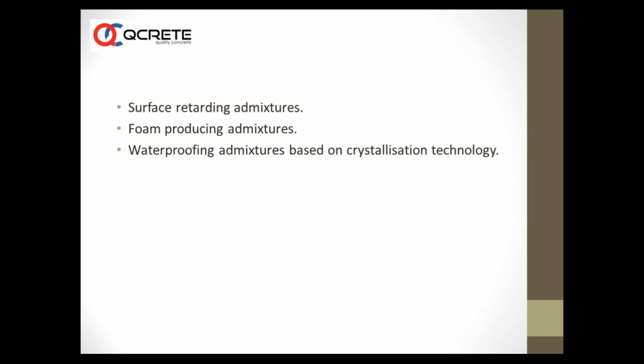Then you have surface retarding admixtures, used when you need architecturally or aesthetically pleasing concrete. You coat this set retarding admixture on the form liner or formwork. Concrete is placed, and the next day when you remove the formwork, the surface retarding admixture reacts with the surface cement particles, removes them, and you get exposed aggregate surfaces.